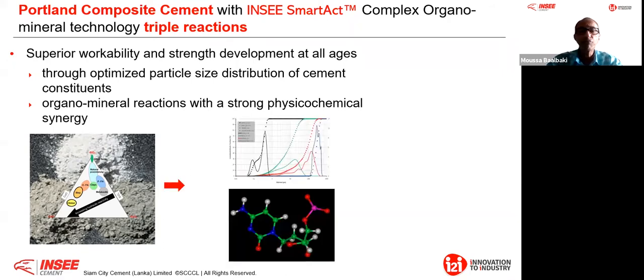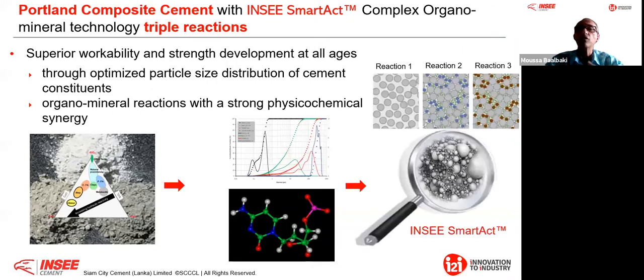And at the same time, if we combine the chemical part with the physical part, we are able to have a very strong physico-chemical synergy. I will explain it later. That is important because when you move from normal concrete to high performance concrete, as I said, it is not only about the compressive strength, because you achieve compressive strength if you look after the water cement ratio to a certain extent. But if you look at the porosity of concrete, you can have two concretes with the same compressive strength, but one has a higher permeability than the other. And that is exactly what I'm talking about here, the triple reaction.